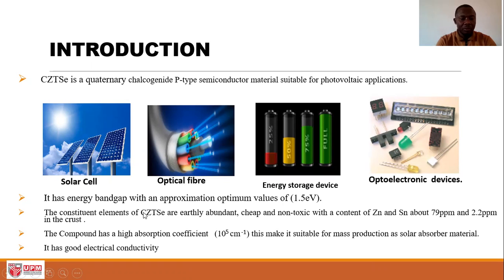The constituent elements of CZTSe are earth abundant, cheap and non-toxic, with a content of zinc and tin at about 79 ppm and 2.2 ppm in the crust. The compound has a high absorption coefficient of 10⁵ per centimeter, and this makes it suitable for mass production as a solar absorber material. It has good electrical conductivity.